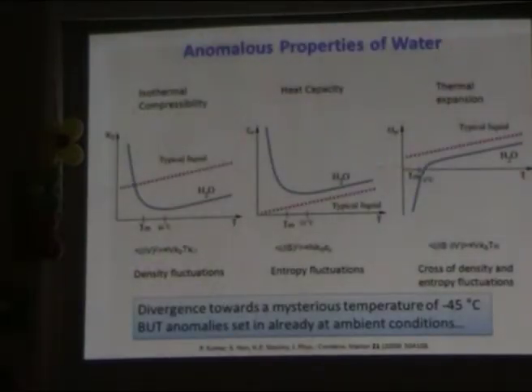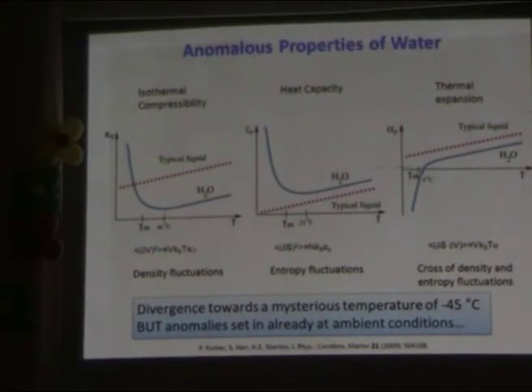Now, you've seen this, so I will only focus on a couple of aspects here. We have the isothermal compressibility, the heat capacity, and the thermal expansivity. What's characteristic of all three is that they depend on fluctuations in the liquid. We have volume or density fluctuations determining the isothermal compressibility, fluctuations in the entropy determining CP, and the cross correlation between them for the expansivity. Now, we have this divergence, and the crazy thing with water is that fluctuations in the liquid increase as we cool. That's a direct indication that these fluctuations have a different origin than thermal.